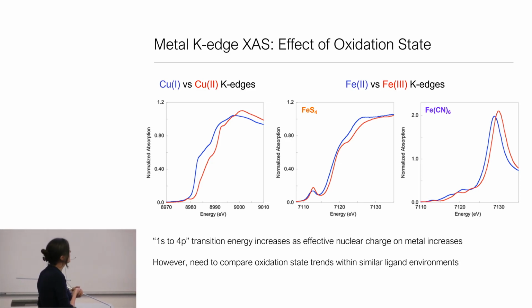But what I'm comparing here also are different iron 2 and 3 comparisons. And so these are iron tetrathiolate complexes where we have a ferrous or iron 2 form and a ferric or iron 3 form. And you see the edges shift up, not quite as much as they did at copper, but they do shift up in energy with oxidation state. And something similar happens when I compare Fe(II) and Fe(III) cyanide. There's also a similar shift in the edge.